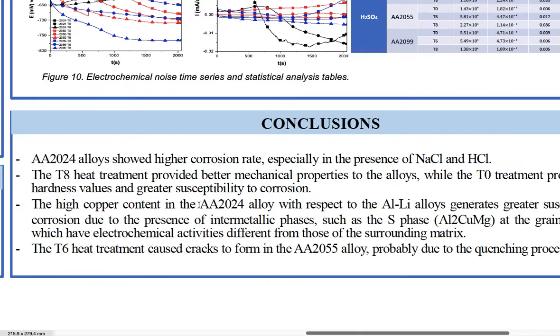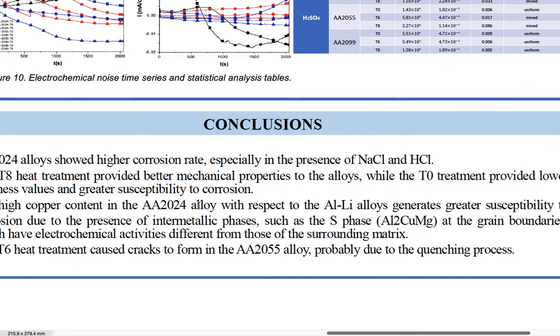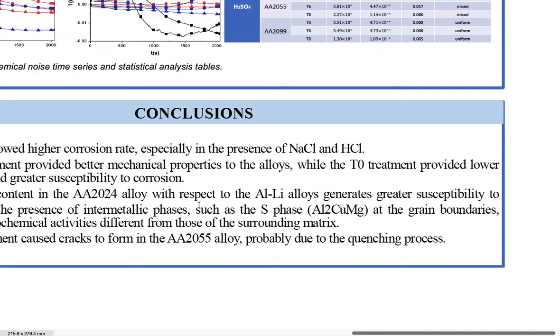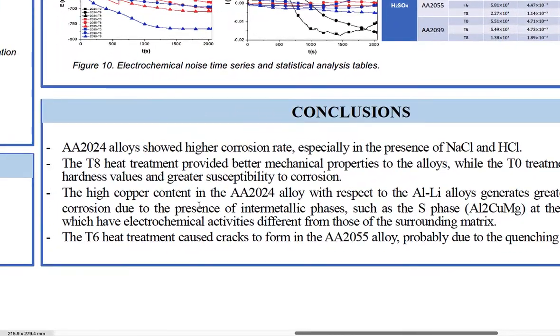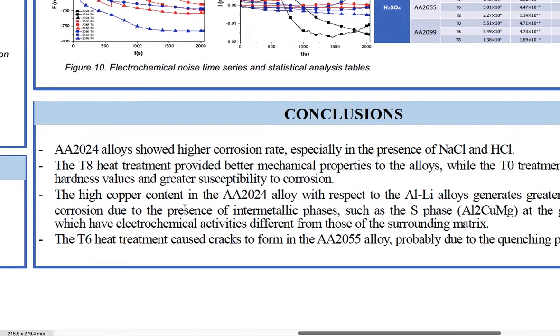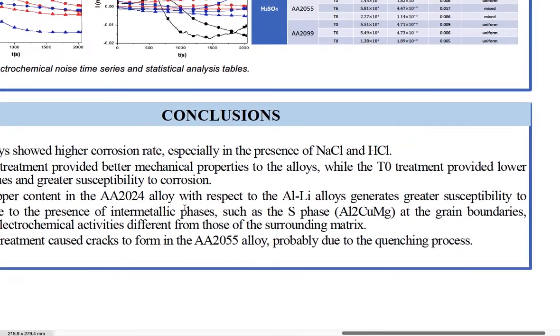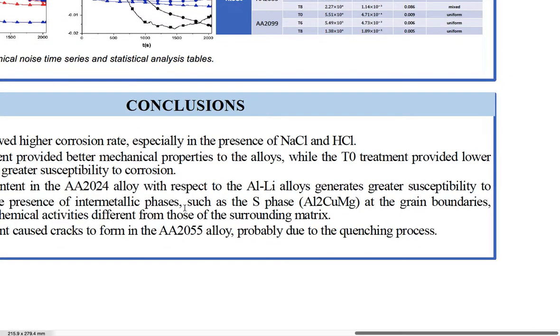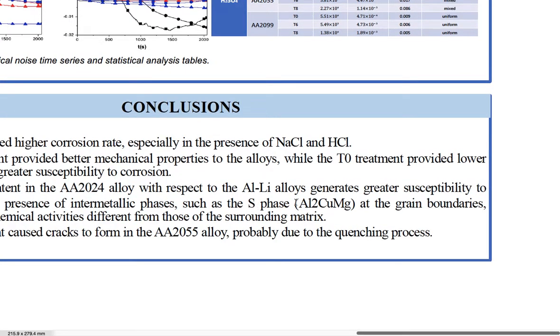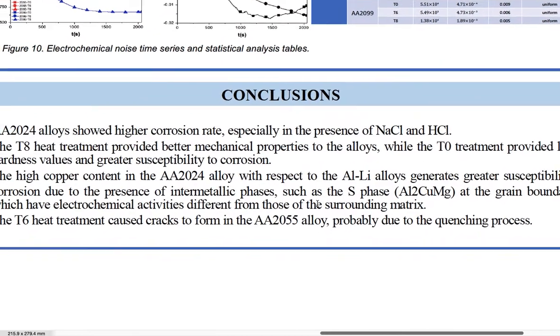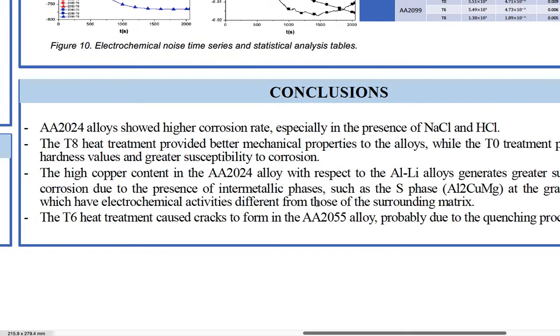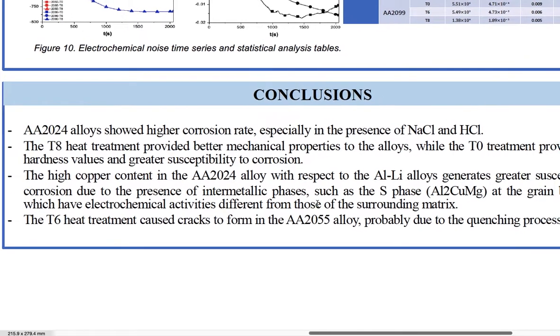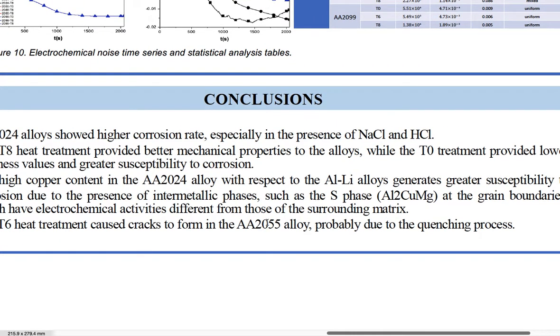The high copper content in the 2024 alloy with respect to the aluminum lithium alloys generates greater susceptibility to corrosion due to the presence of intermetallic phases such as the S phase, Al2CuMg, and the grain boundaries, which have electrochemical activities different from those of the surrounding matrix. The T6 heat treatment caused cracks to form in the 2055 alloy, probably due to the quenching process.